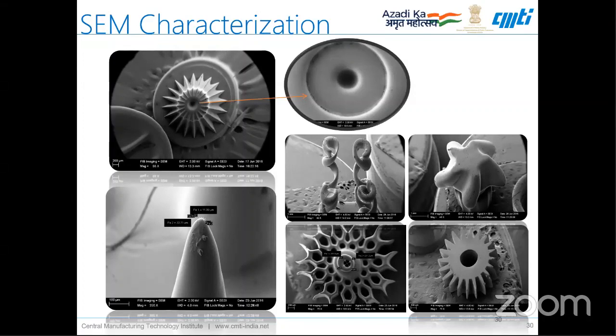A few tens of nanometers surface finish we directly get on the fabricated component once you remove the excess resin from the cube components. You can see we have also tried the micro needle here. There will be no stepping effect. You will get a smooth curvature over the micro components. There will be no stepping effect here. We are able to achieve the tip of the microneedle at about 11 micron in this image. It is possible to achieve up to 5 micron. That is the capability of the equipment we have in house.